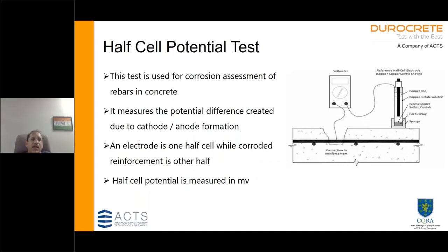We discussed that visual inspection is the first and foremost thing that we must do as part of conditional assessment. Then there are certain tests that we do on the concrete, and one of the most commonly used is the half cell potential test. This test measures whether corrosion has initiated inside the concrete. One very important thing is that where there are visible signs of corrosion, where you have corrosion cracks along the line of reinforcement, this test does not add value. This test is used where there is no visible corrosion but the process has started inside, and you could take corrective measures in the course of time. These days there are a lot of paints available that can stop ingress of water and moisture, so you can delay the process of corrosion if it is detected early.